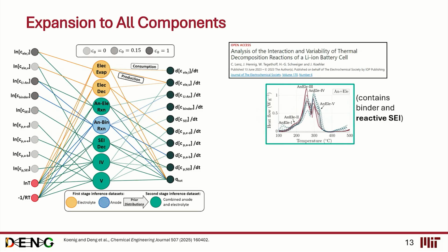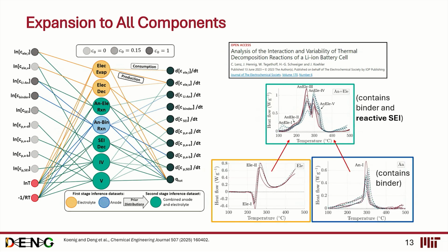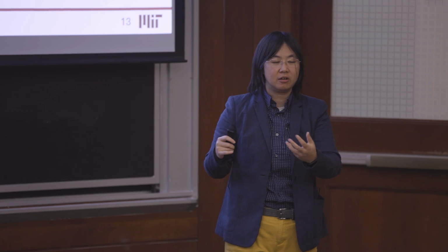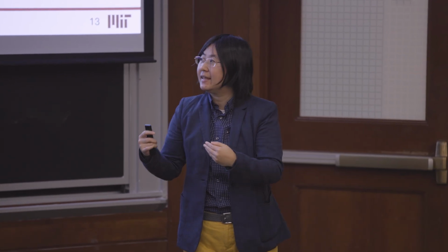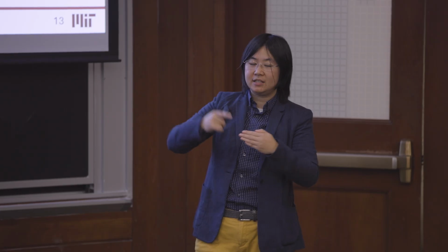Essentially, we have a very nice set of experiments. They did the experiments as much as they could. For example, if they could have a clean experiment with the electrolyte, they can just take the electrolyte, put it in the oven, put it in the DSC and run it. But in other cases, such as the SEI layer, it's not possible for them to peel that off. So they have to take the entire electrode to the devices, right? I'm skipping a lot of the details, but essentially sometimes we can directly model the component. Sometimes we need to consider that the system is not clean enough, so we need to do it stage-wise.